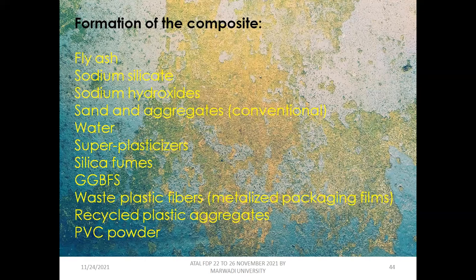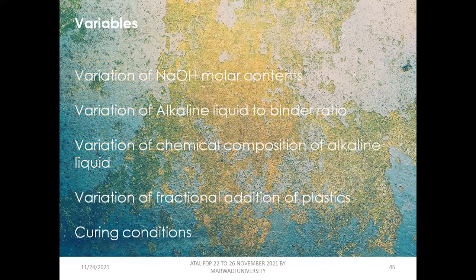of the total mix, and superplasticizers, silica fumes, GGBFS, that is ground granulated blast furnace slag, waste plastic fibers, again the recycled plastic aggregates, and we also utilized PVC powders to an extent. So in this, we had some variables like a variation of the NaOH molar contents and variation of the alkaline liquid to binder ratio.